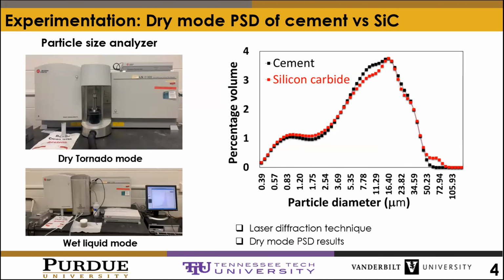And so our base condition was a dry-sized powder particle size distribution. So we manufactured the silicon carbide until the silicon carbide distribution looks like cement, as seen in the graph. The result shows that both solids were remarkably alike, as seen by the overlap of the two curves.